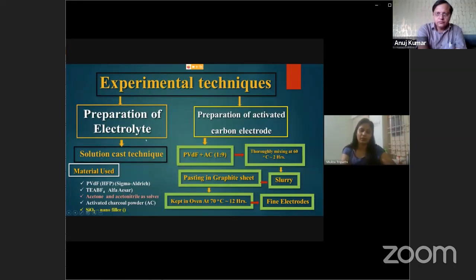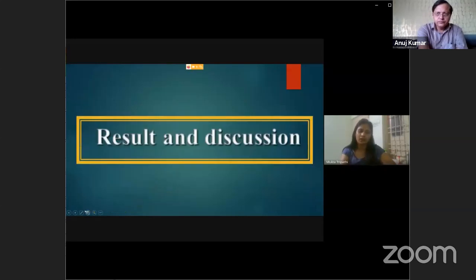However, this one is your electrolyte material. For the electrolyte material, we use the solution cast technique, and these are the materials we have used: PVDF HFP polymer, TEABF4 as a salt, acetone and acetonitrile as solvent, and activated carbon as we have synthesized in our laboratory, and nanofiller, that is SiO2. Let's see the discussion related to that.